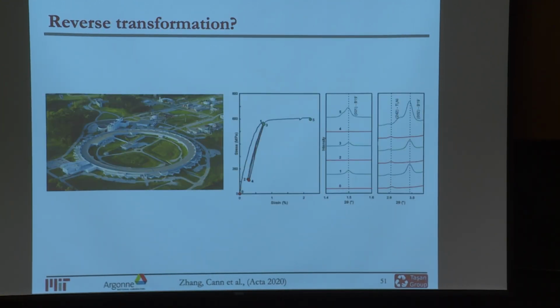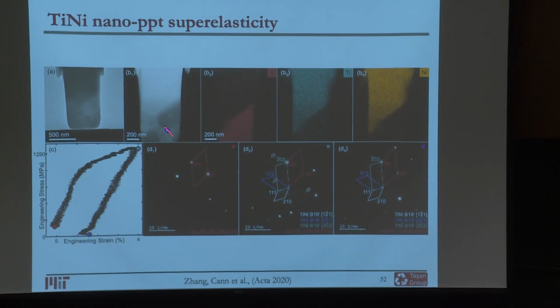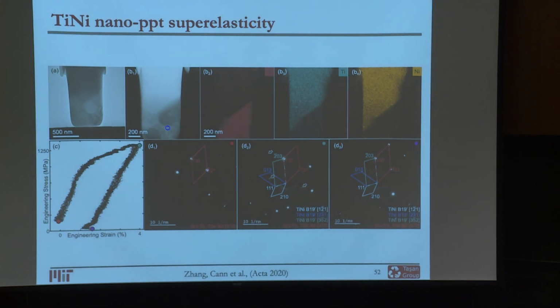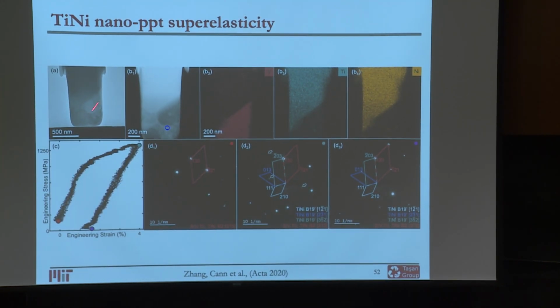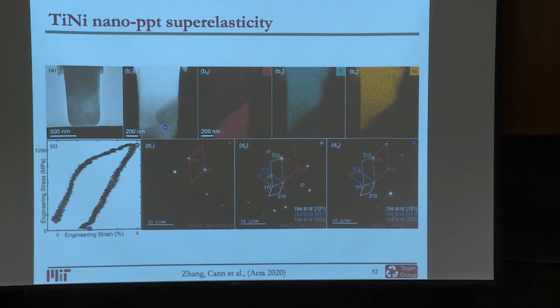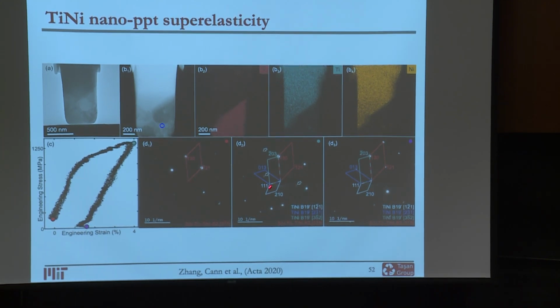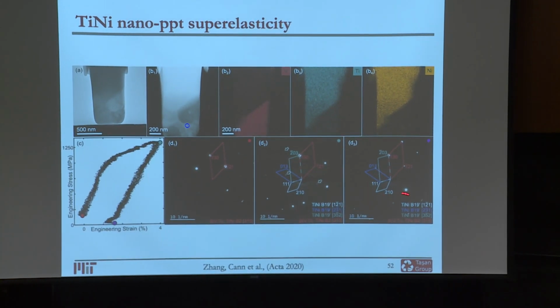So actually looking at the synchrotron measurements, we are not fully sure whether you have the forward transformation and back transformation taking place. So the only other solution you can do is go to a transmission electron microscope and actually carry out an in situ deformation experiment, where you carry out selected area diffraction on each individual titanium nickel feature that you can find. And by doing that, we've demonstrated that, again, you can have the forward transformation. So this is from B2 to B19 prime, and then reverse transformation, although this reverse transformation in this case didn't fully take place.